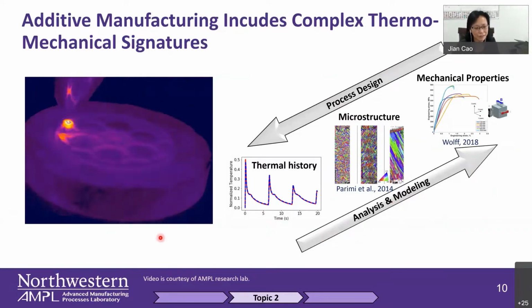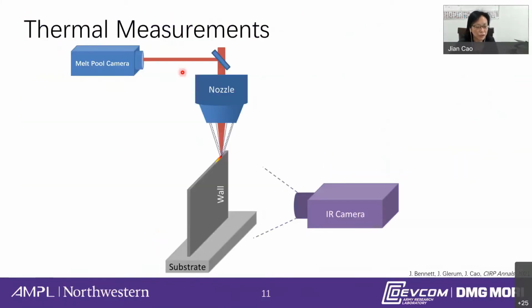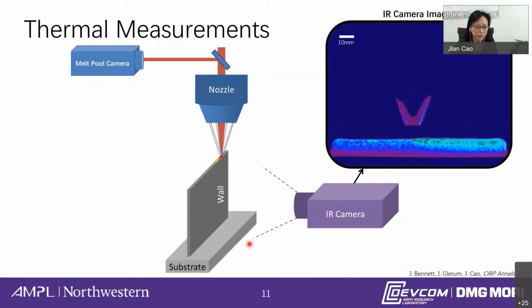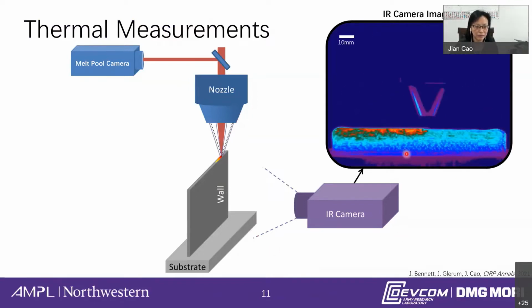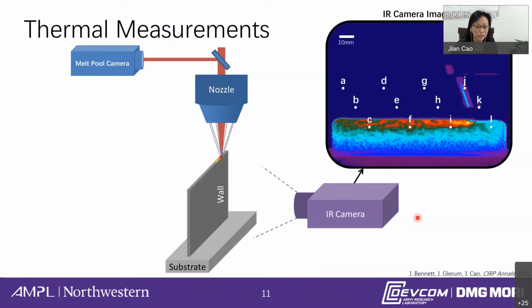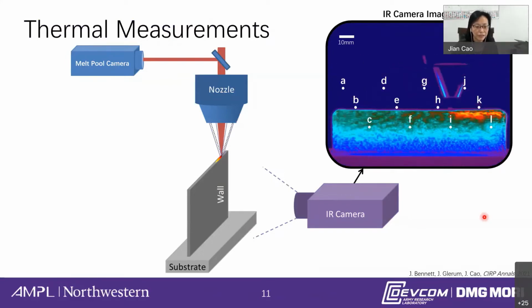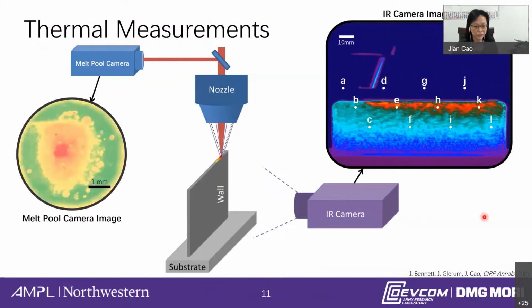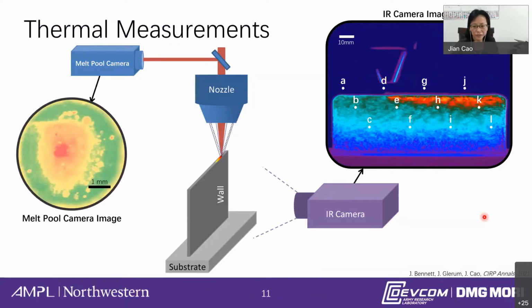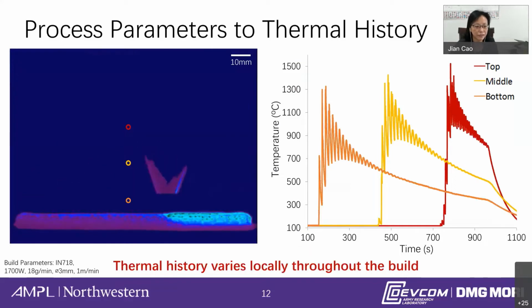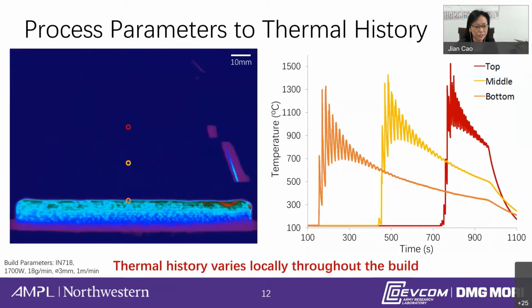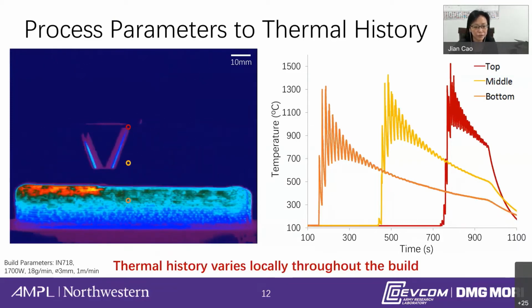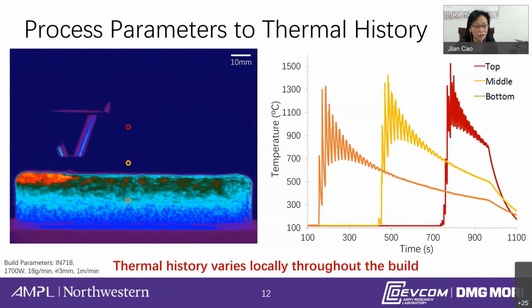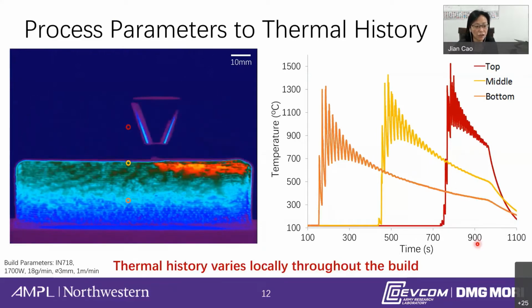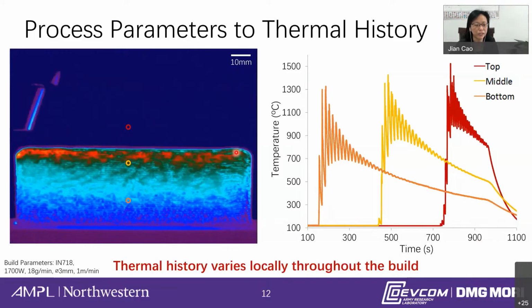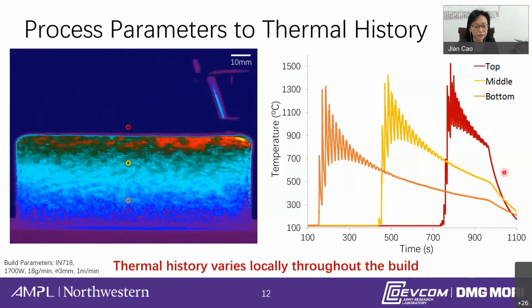But the key point that we want to do is to see how we can control the properties. So you have the nozzle coming down the wall, and one of the first works that we have done is looking at the IR camera, and then you can cut the samples from the single wall, and also look at the correlation. That setup is relatively easy, and you can see the temperature readings at different points. As you build up, you can also see that the top ones, the red ones, even though you use the same laser power, because of the heat accumulation through the build, have an overall higher temperature.